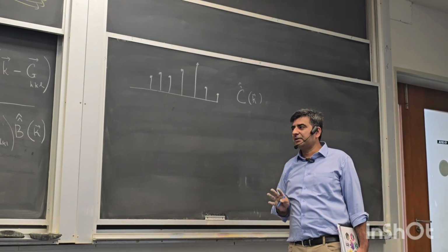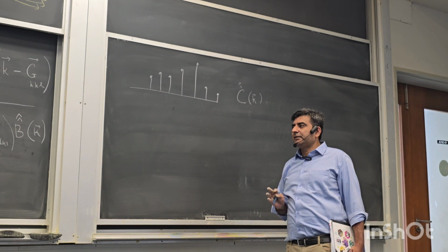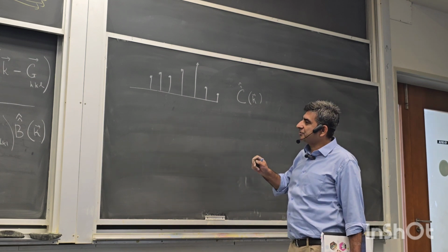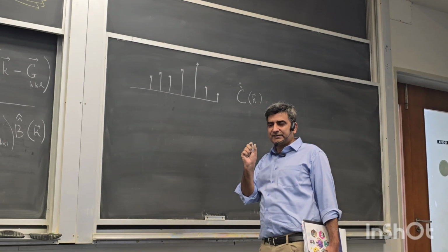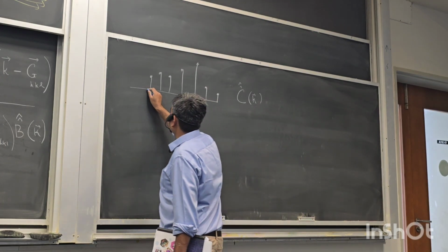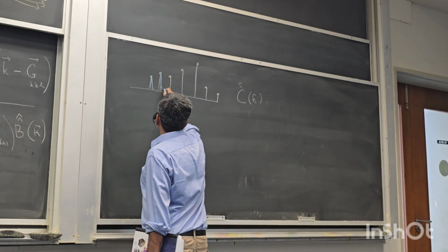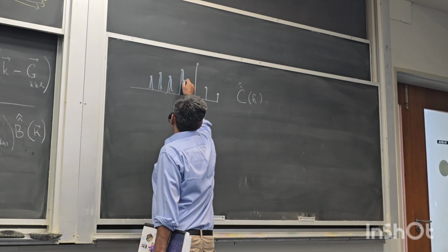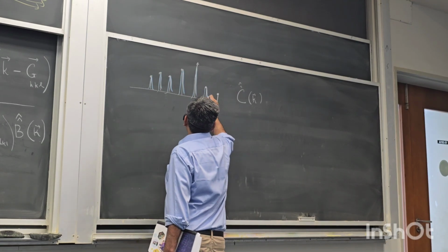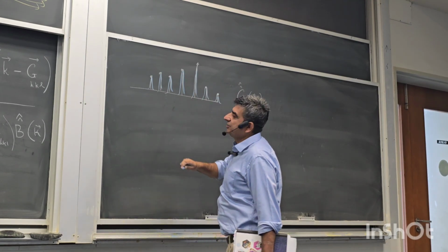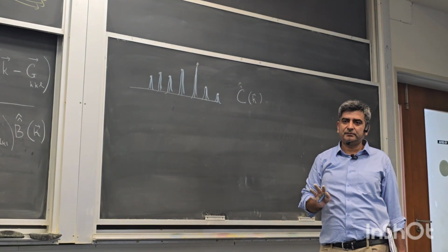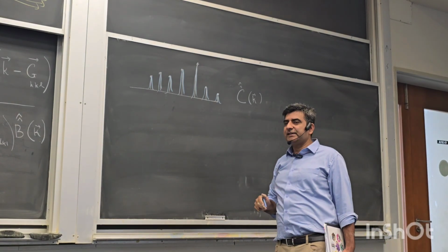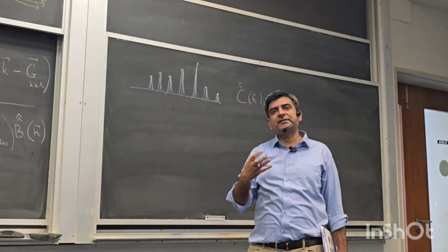Another thing you might notice is that in diffraction patterns you never get Dirac delta functional peaks. There's some spread, so you get peaks of this kind. This dispersion on each point, this width on each point, can come from different sources. One of the sources is that the crystal itself is of finite size.